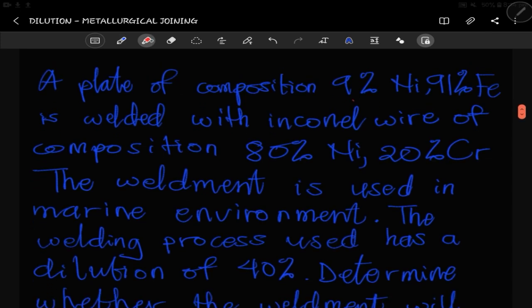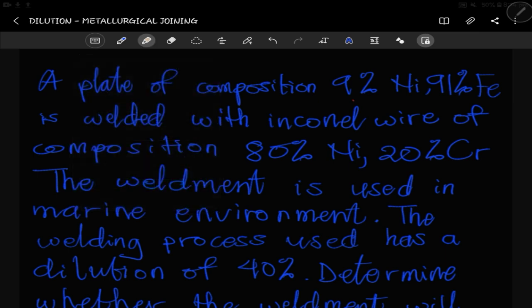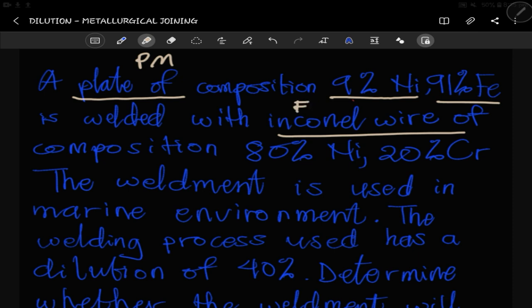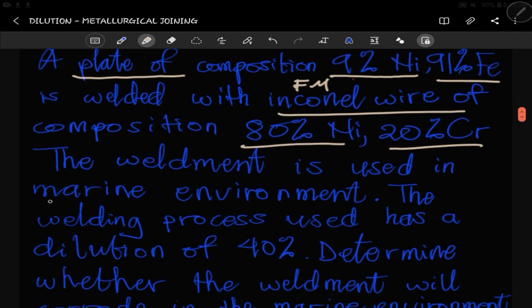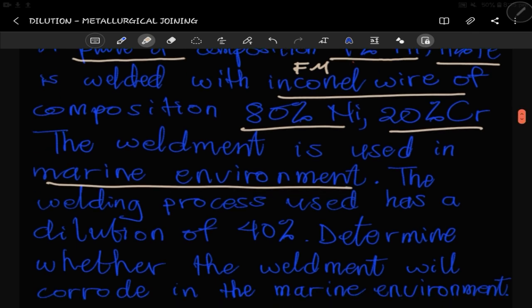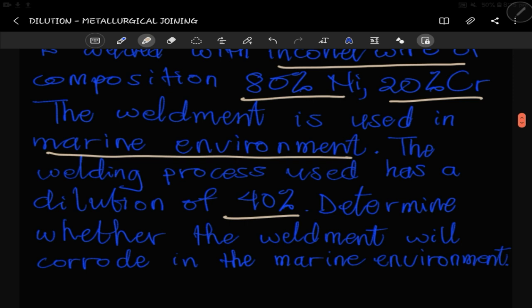Let's see what this says. A plate of composition 9% nickel, 91% iron is welded with an inconel wire. Basically, this is our parent metal. It's welded with an inconel wire, and this becomes our filler metal, of composition this and this. The weldment is to be used in a marine environment, and the welding process used has a dilution factor of this. They didn't specify anything else, they just gave the dilution factor. Determine whether the weldment will corrode in the marine environment.